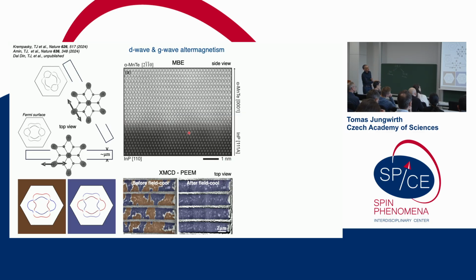First, you need to start with a perfect single crystal epilayer. So this is manganese telluride grown by molecular beam epitaxy, virtually without any defects on a large scale. Now, you have this hexagonal lattice, and it has basically 3 equivalent easy axes in the plane. But they can choose which of the easy axes they will get by making bars which are, let's say, a few microns wide. If you make these bars, the easy axis, because of magnetic anisotropy, will choose to align along the bar direction. So they can now choose one out of these 3, but they cannot distinguish the time reversed domains.